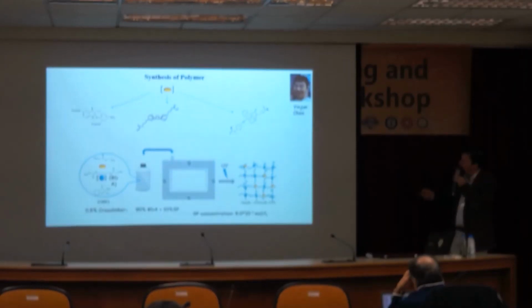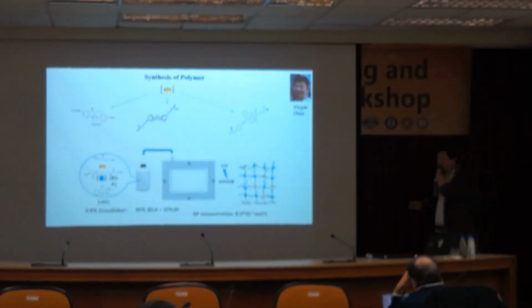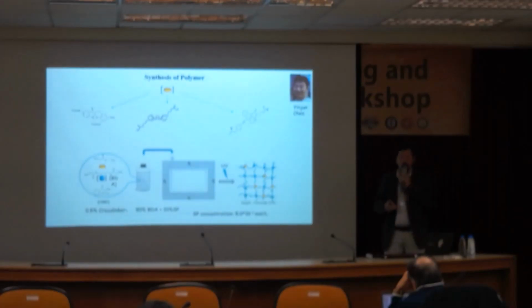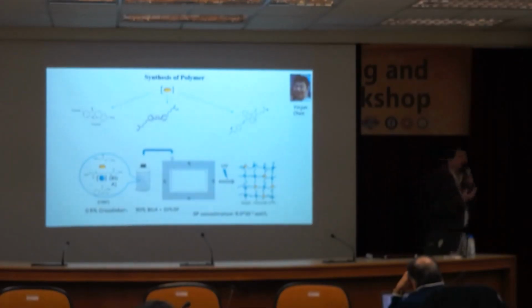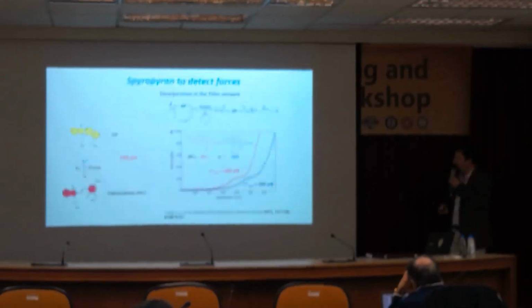So to synthesize the polymer, this is the work of my talented student Yinjiu Chen. You can incorporate here this particular molecule, either one of these three, as a crosslinker. When you make your first network, you introduce all the ingredients in this mold, and instead of using this blue crosslinker, which is the standard one, you put some, typically of the order of 0.1%, that you introduce. So it really doesn't change the properties of your material, which is something we can check. But you introduce a certain number of these bonds that are mechanically active.